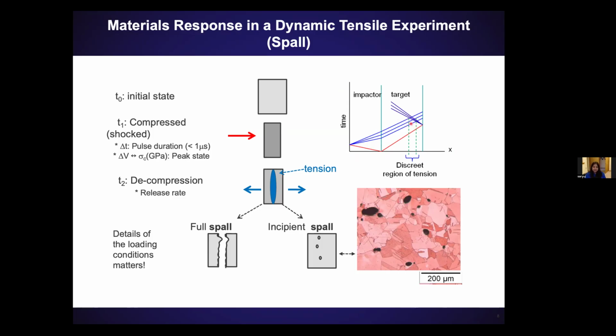When these waves intersect in a region, and you can imagine already by changing the ratio of the thickness of target to impactor, you could essentially get these waves to intersect anywhere or not intersect at all. But because a lot of the work we do in my team is associated with spall failure or damage in material, we tend to want these waves to intersect by design so that we can open regions of failure in the material. This is what it looks like in a schematic form. You might get a state of tension where these waves intersect, and that's why you nucleate voids.